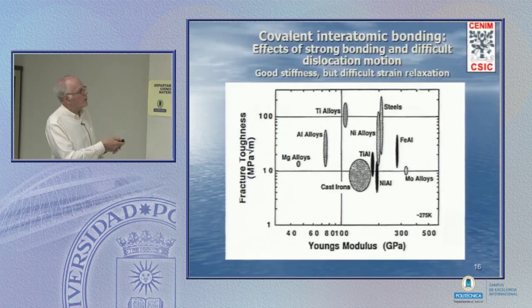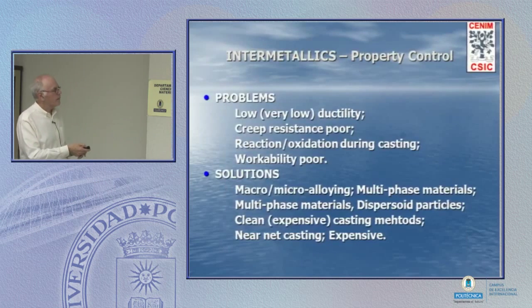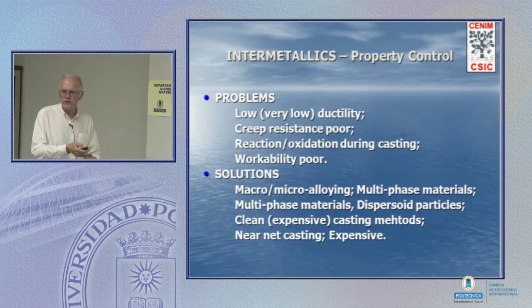Toughness and Young's modulus. Here's steel. The steel's range of toughness, typical modulus around 200 GPa. Here's the iron aluminide. Toughness has come down somewhat, depending on which aluminide you're looking at, and stiffness has gone up. Titanium alloys and TiAl. We're always increasing modulus and lowering toughness. So, the good news is that we have the possibility of increasing strength and oxidation resistance and stiffness and so on. The bad news is watch out, especially for ductility, and also creep resistance is sometimes not too good.